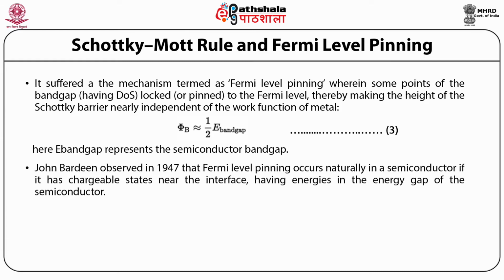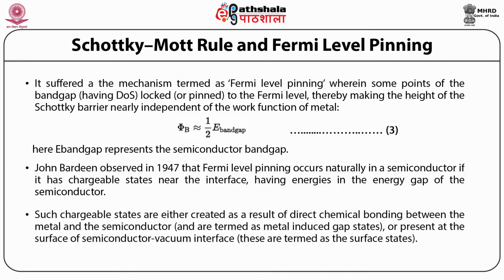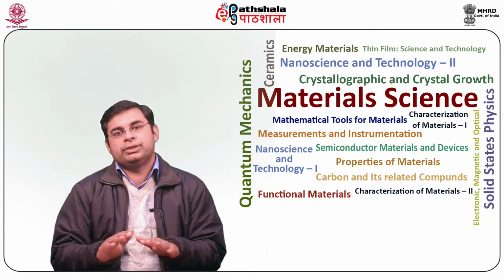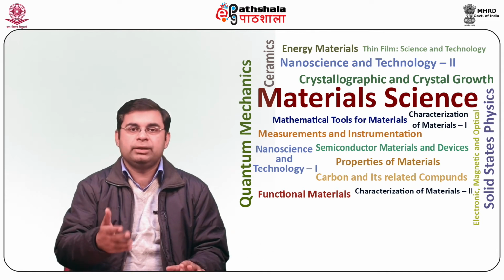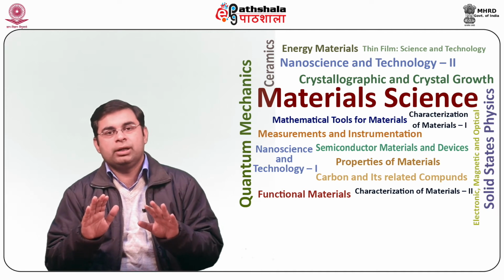John Bardeen observed in 1947 that Fermi level pinning occurs naturally in a semiconductor if it has chargeable states near the interface having energies in the energy gap of the semiconductor. Such chargeable states are either created as a result of direct chemical bonding between the metal and the semiconductor, and are termed metal-induced gap states, or are present at the semiconductor-vacuum interface, that is, they are termed surface states. These extremely dense surface states trap most of the charges donated by the metal, thereby shielding the semiconductor from the metal.